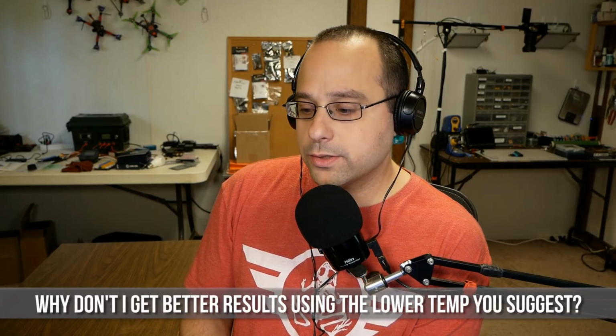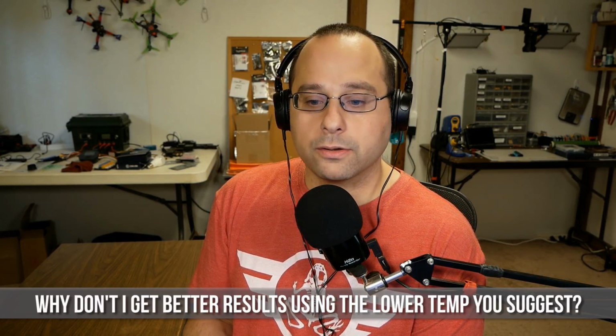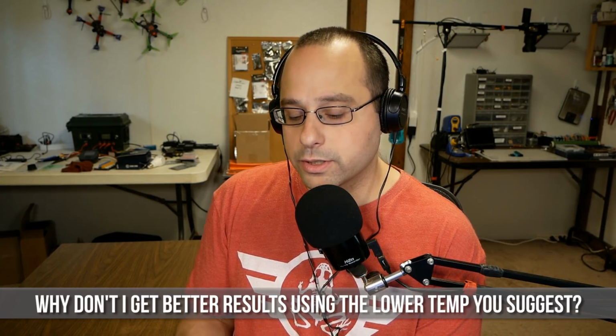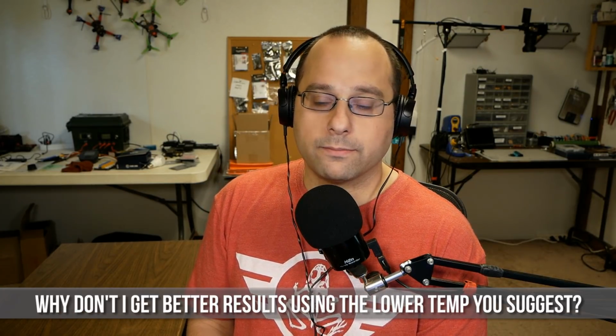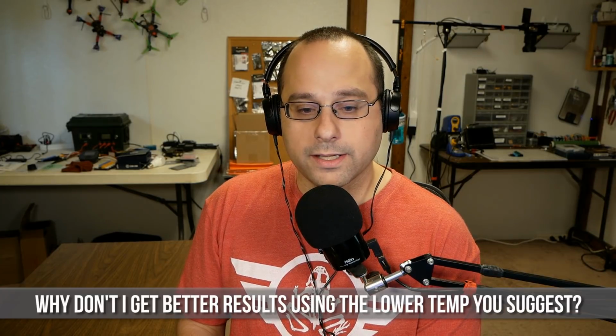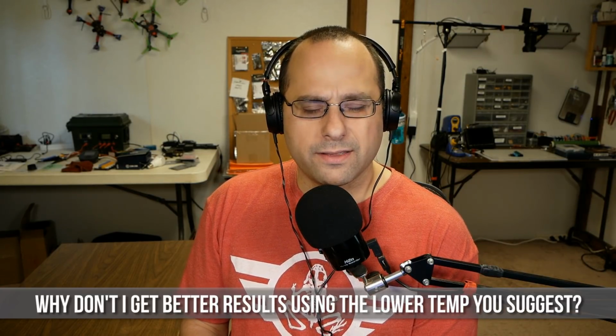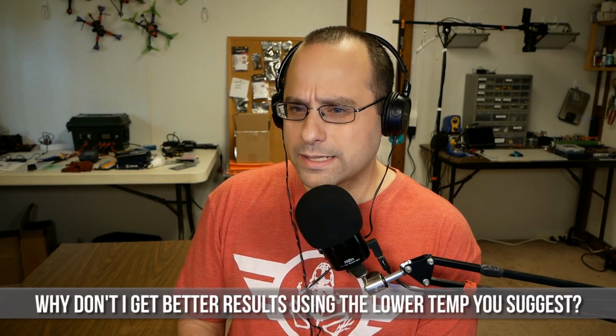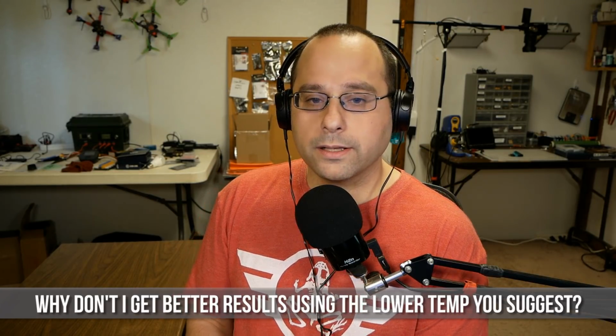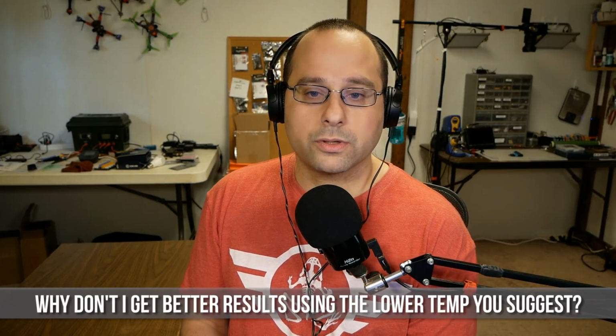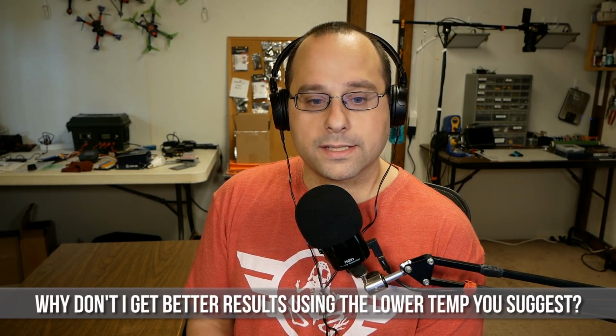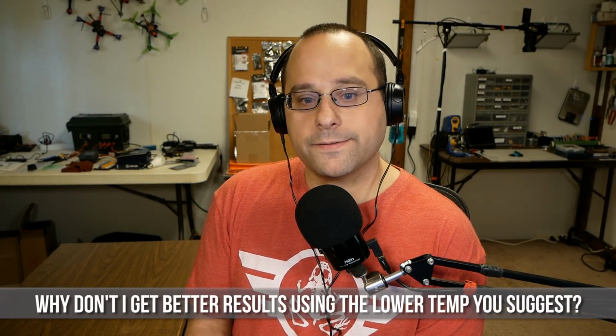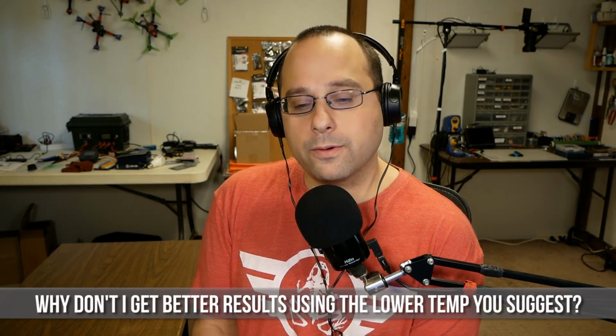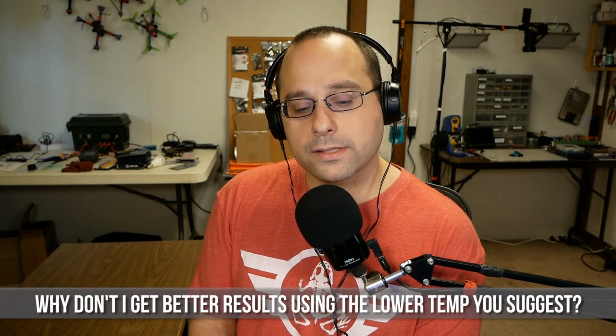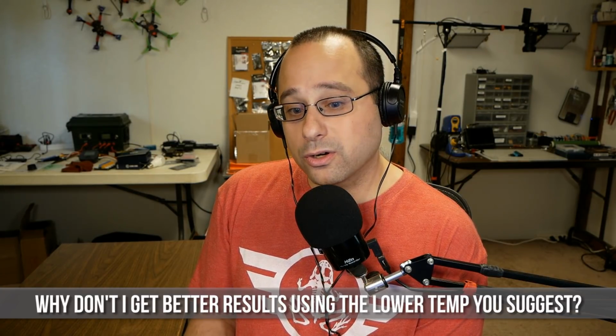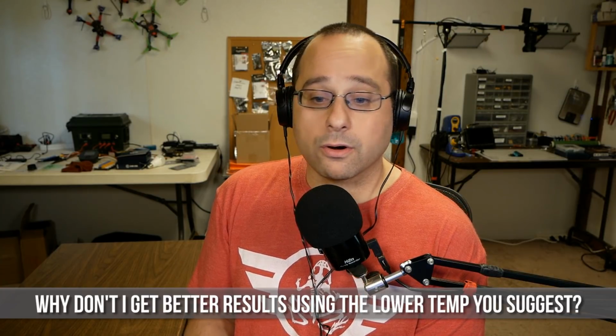Okay. Now, here's a question I had after I took your advice and started trying to use lower temperatures. Just for your perspective, I have my iron set in Fahrenheit, but I typically use about 750, which I think is about 400 centigrade, more or less. Yes, that's correct. I tried lowering it closer to what you were saying, like 600, 625. And I found it hard to quantify what I didn't like. I didn't find that I was getting very good results. It felt like I had to apply the iron longer, and it was harder for me to get good joints.